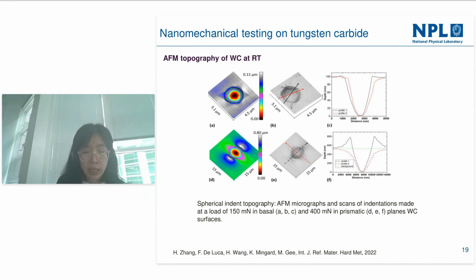And the AFM line profiles in figure C of the indent don't show any large sink-in or pile-ups at the indentation load used. This observation is consistent with previous research showing that dislocations glide downwards along the 1010 prismatic slip planes and accommodate the volume change created by the indent.